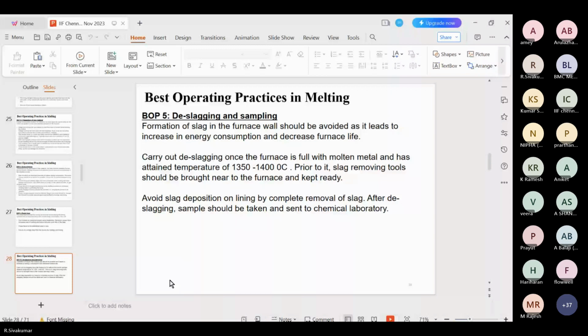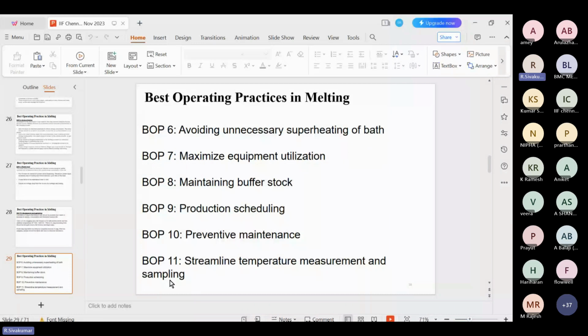What are the other practices? Avoid unnecessary superheating of the bath, maximize the equipment utilization, and maintain the buffer stock, that is, the raw material stock should be available as much as possible. Proper production should be scheduled, and the furnaces should be run based on that schedule only. Otherwise, every day they are running for 12 hours. Then for the 12 hours the furnace is off, every day's cold start also leads to more energy consumption. So these should be avoided, and preventive maintenance should be carried out at regular intervals, and streamline the temperature measurement and sampling. Already discussed.